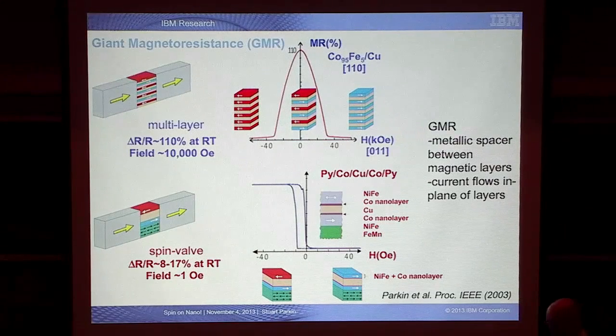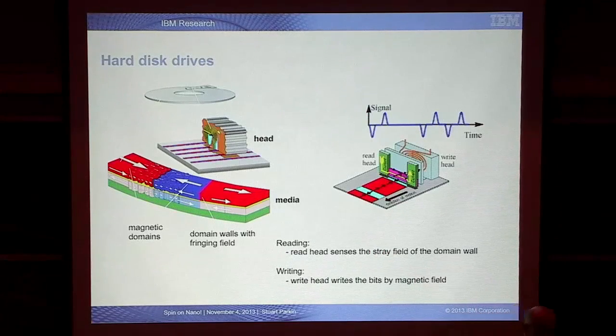And this is what we invented, and then we were able to show we could use this in a very important application, which is that of a magnetic disk drive. So a magnetic disk drive essentially has today glass disks shown here, and each surface of this disk is covered with a magnetic film. And this magnetic film, a rather complex magnetic material, is magnetized in tiny regions, shown here as these red and blue regions, around the circumference of this disk. And essentially, information is stored as the boundary between one magnetic region and the next. It's these boundaries that store the information, a 0 or a 1. If we have a boundary, that's a 1. If there's no boundary, then it's a 0.